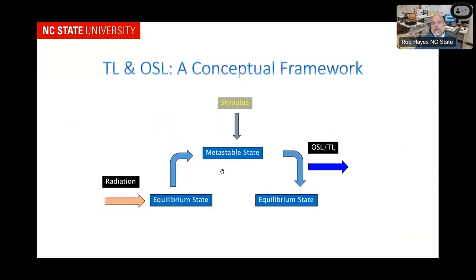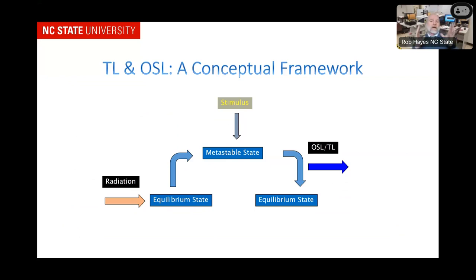After I expose something to ionizing radiation and start trapping electrons and holes, I put a little bit of energy into one of these trapped electrons, it goes up to the conduction band, and when it recombines with a hole, that energy difference is given off as a photon that I can capture with a photomultiplier tube. I can do this extra energy input with either heat or a laser, filter out the laser light, and then look for this output signal. This is what we do with thermal luminescence and optically stimulated luminescence.